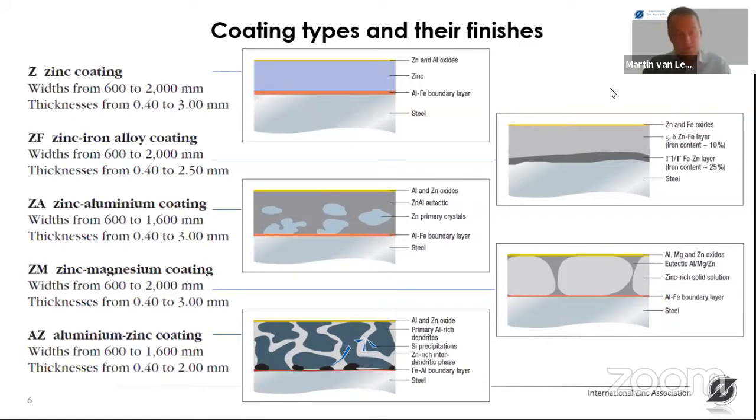And then, last but not least, the Galvalume process is called GL. The coating is called AZ from aluminium zinc. The products are delivered with a normal spangle. Normal spangle means a finish with a metallic luster, which is the result of unrestricted aluminium zinc crystal growth during normal solidification. If a pronounced spangle is desired, this shall be indicated especially at the time of inquiry and the order.